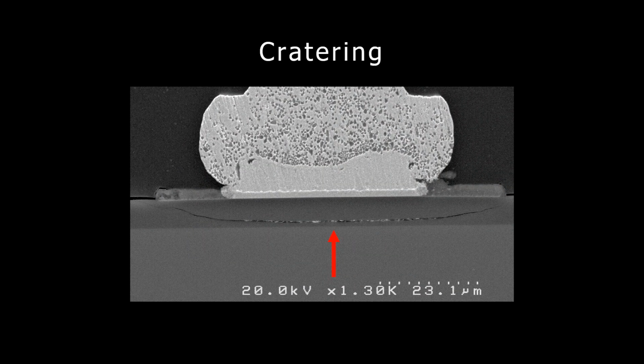Cratering is a cracking of the dielectric under a pad. Cratering is caused by improper setting of the bonding tool. When the crack is completely under the pad, it is not visible using a microscope. This cratering was discovered using cross-section.